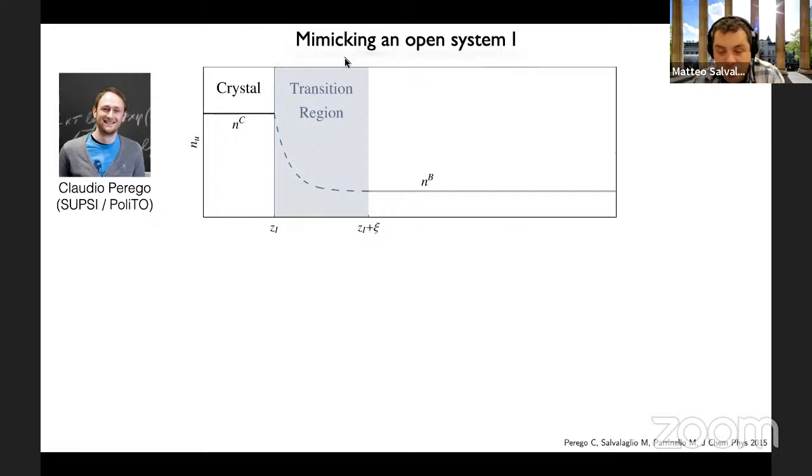directly in a simulation. When we perform simulations of crystal growth instead at the atomistic scale, what we observe is that the concentration in the liquid phase changes as the system moves along and progresses. And so here is where this idea of CμMD, or constant chemical potential molecular dynamics, comes in and helps us essentially mimicking an open boundary system.